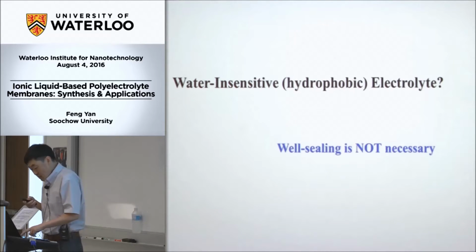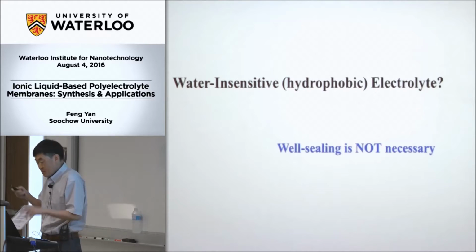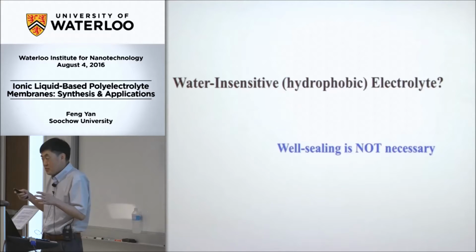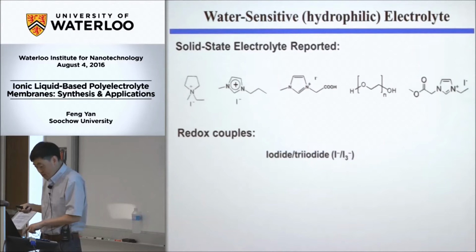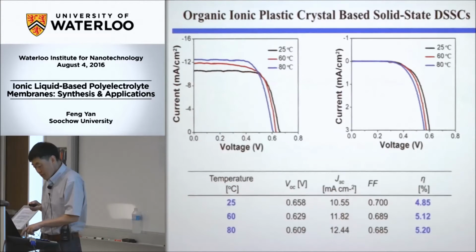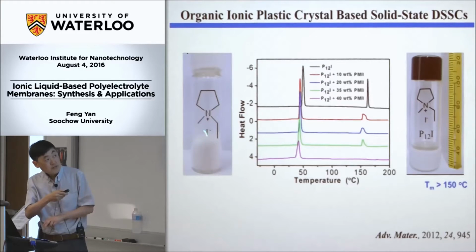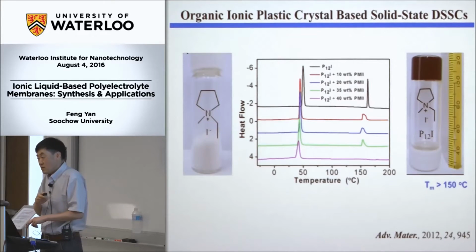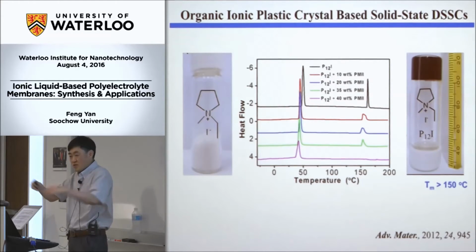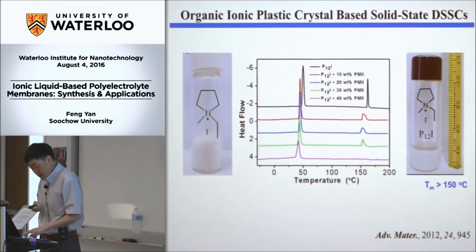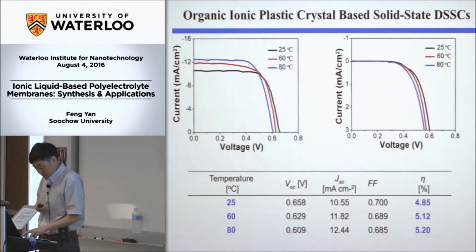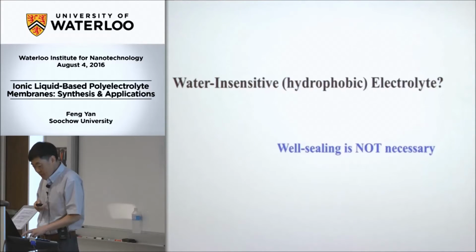It will absorb water from the atmosphere, so the device should be fabricated in the glove box. As you can see here, this is a hydrophilic compound. If you put it at room temperature, it will absorb moisture. And therefore, maybe there are some problems for real applications.